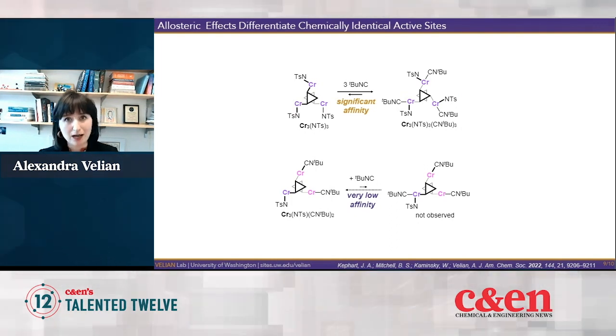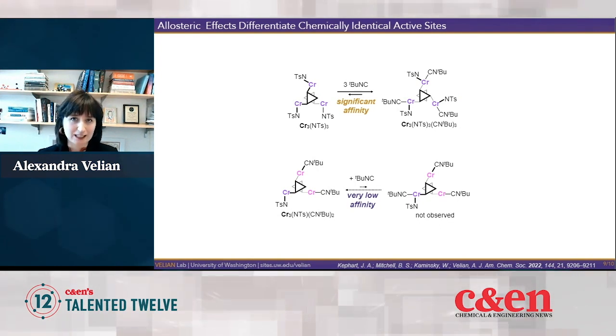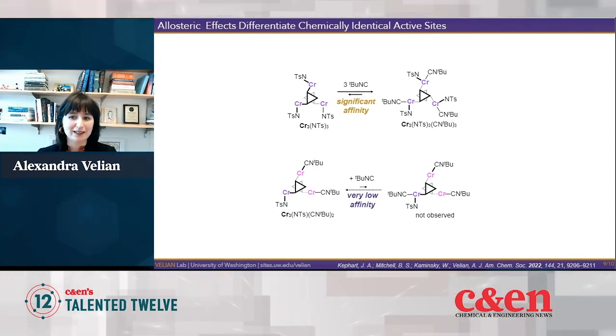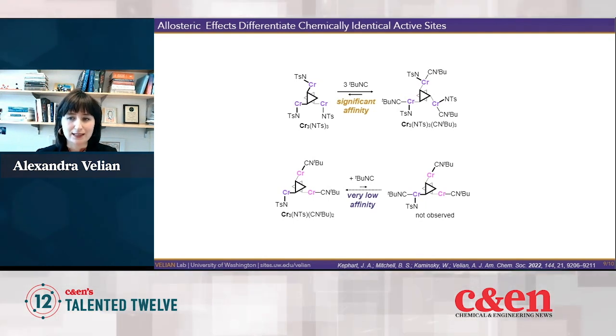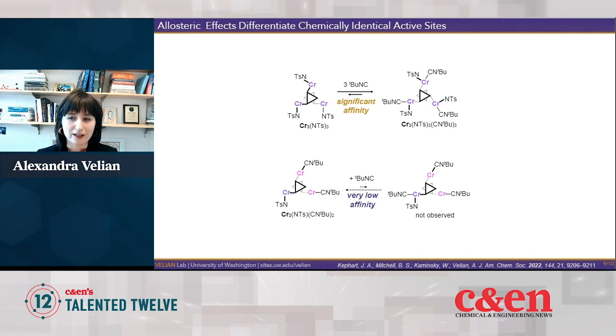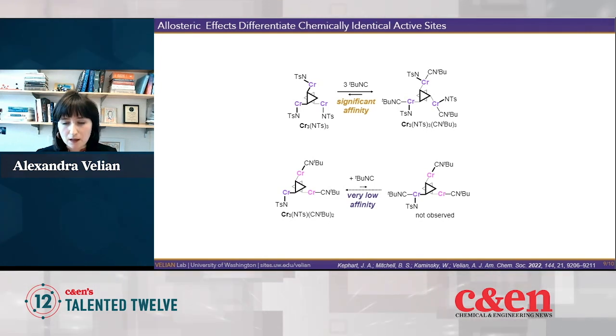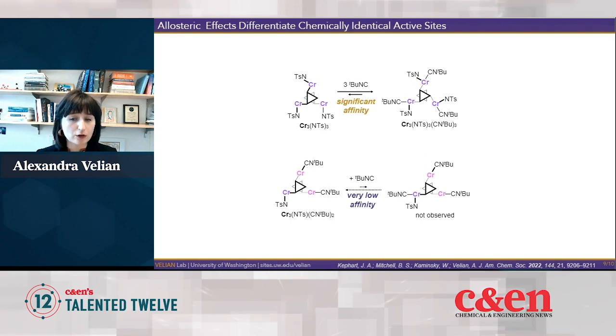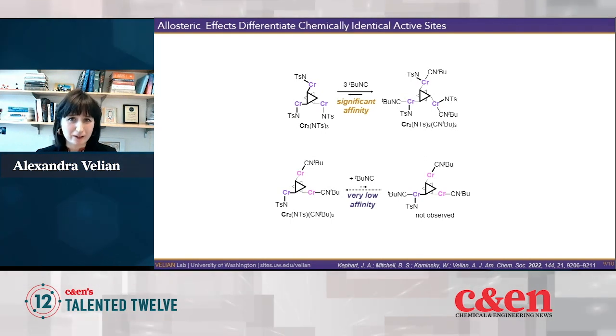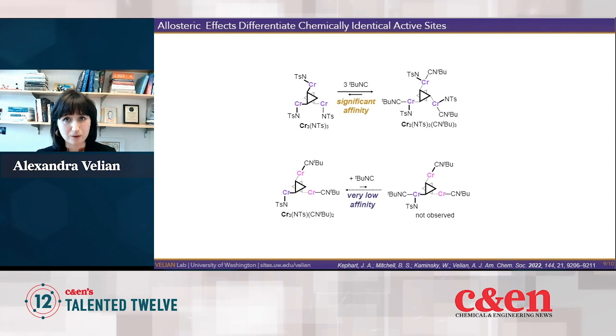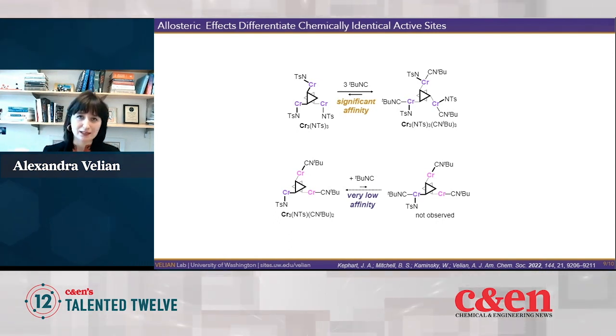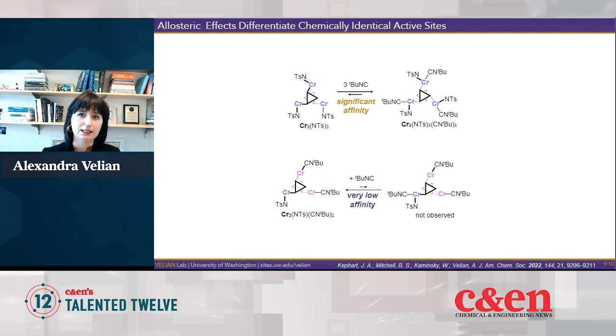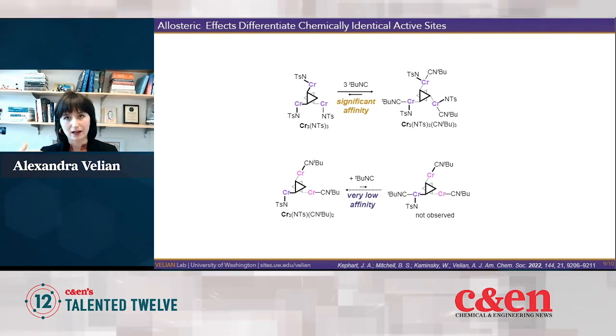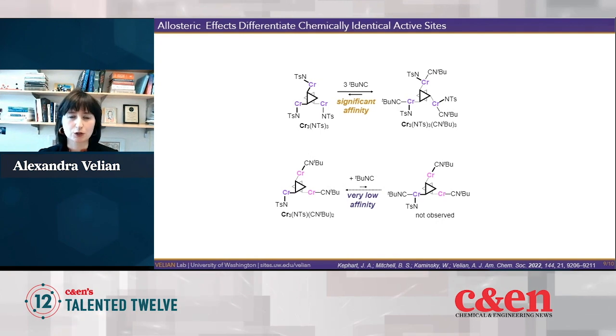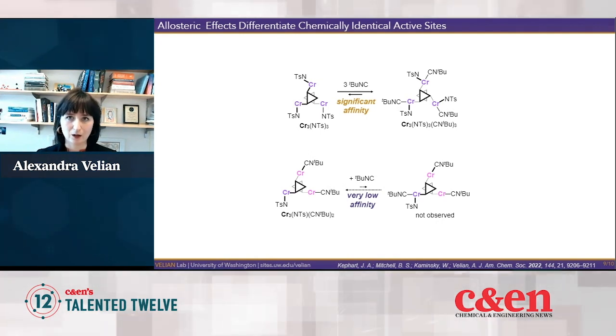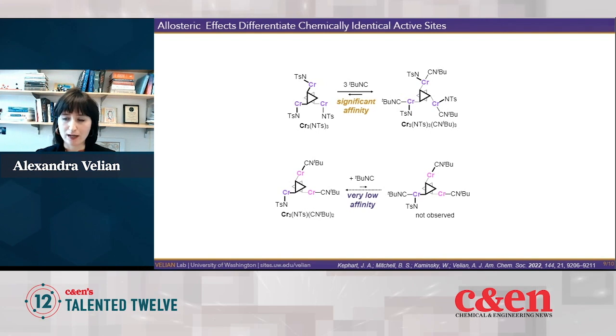It turns out that the tris-imido cluster has a significant affinity for isocyanide to bind and give rise to the steady state form of the catalyst. But in contrast, the monoimido cluster actually has very, very little affinity at this chromium imido edge site for the isocyanide. So what happens at these neighboring sites truly impacts reactivity at the neighboring one. And this inorganic cluster support is essential to communicate and propagate the information from one edge to another.